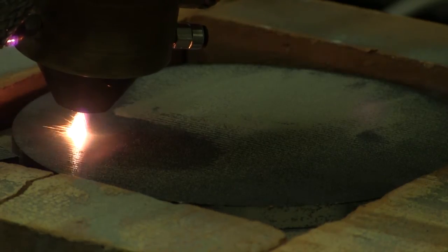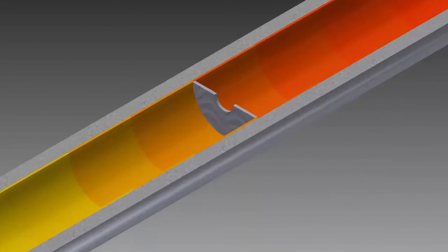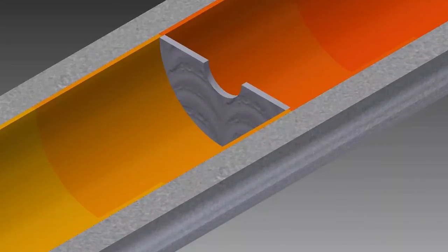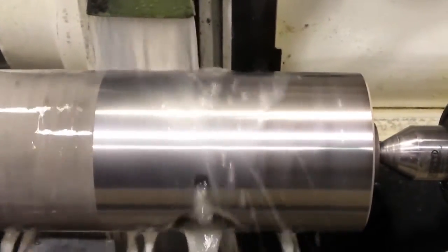In particular, an innovative technique for the production of internally coated barrels with a layer having variable composition was developed. These gradient composition bimetallic barrels are successfully made by first laying different sets of powder feedstock having specific compositions in the inner side of raw barrels, separated by special steel rings acting as dividers during melting. After spinning, optimal composition in each of the barrel sections is achieved.